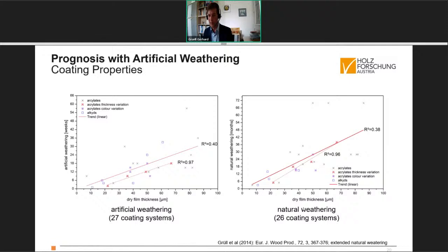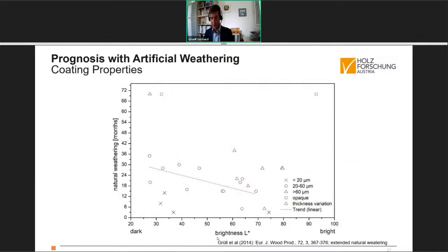And the same result in natural weathering, where 26 coating systems so far have degraded until the limit state, where again the thickness variation of the same system brought forward a nice correlation. And for all systems, there was at least some trend to this estimation. And this is a result for brightness variation. If we measure brightness on the surfaces, is there any trend for the durability in natural weathering? Well, for the semi-transparent systems with a medium build, 20 to 60 microns dry film thickness, we see some rough tendency here that darker pigmentation of these semi-transparent varnishes led to higher durability compared to brighter pigmentation.